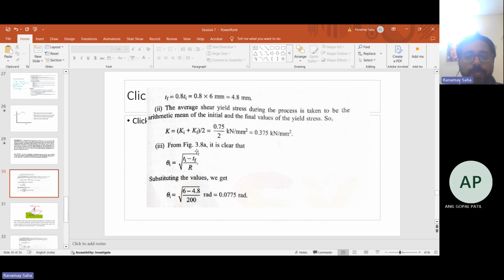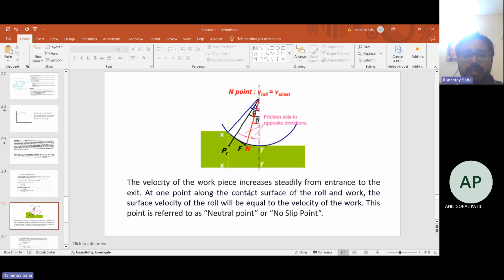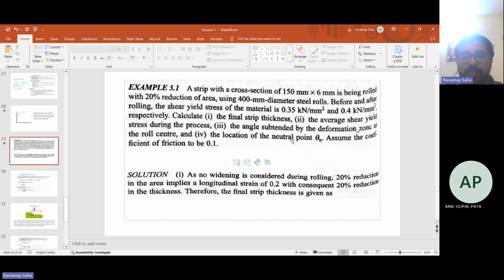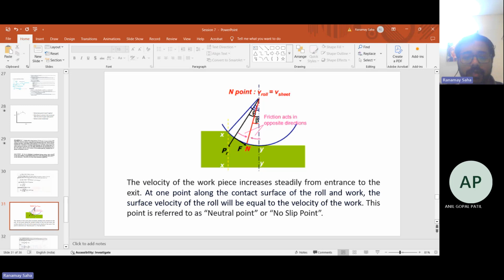And then the angle subtended at the roll center is the square root of the difference in thickness upon the roll radius R, which will give you 0.0775 radians. Okay. The next point is you have to find the location of the neutral point N. So first, let me quickly show you what happens at the neutral point. It is the point where the surface velocity of the roll will be equal to the velocity of the workpiece. In other words, in a sheet rolling process, the velocity of the sheet movement will be equal to the velocity of the roll, right? So that is called the neutral point or no slip point. The velocity of the workpiece increases steadily from entrance to exit, and then it decreases.